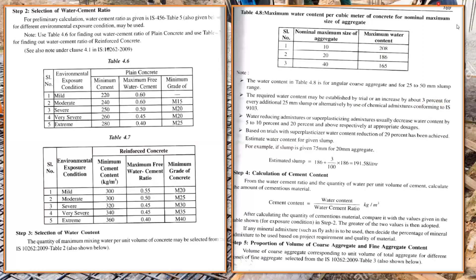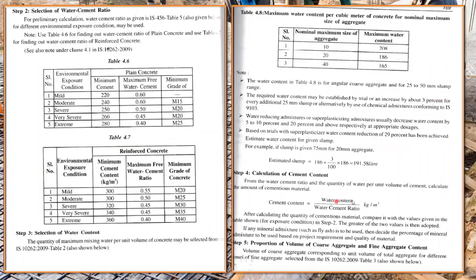For example, if the required slump is 75 mm and the table is based on 50 mm slump, the difference is 25 mm. So add 3% of 186: that is (3/100) × 186, giving the corrected water content of approximately 191.58 kg. Once water content is established, the next step is calculating cement content.